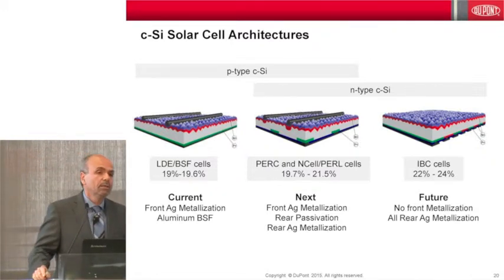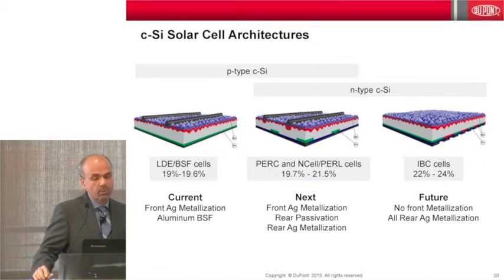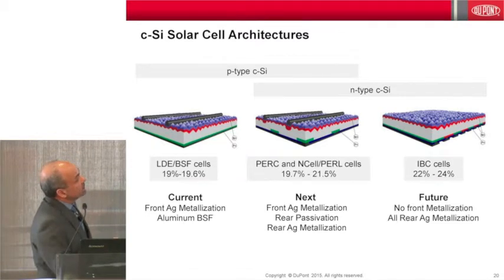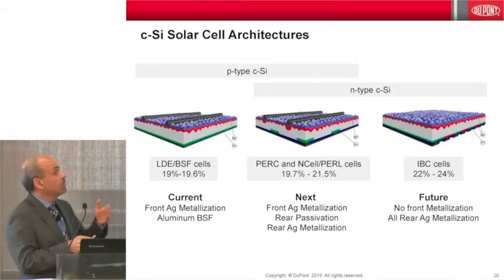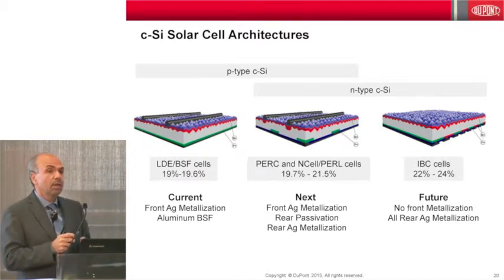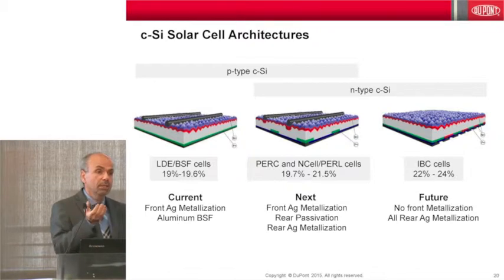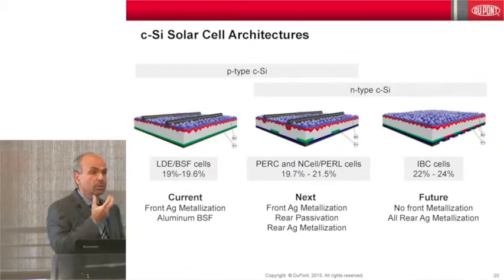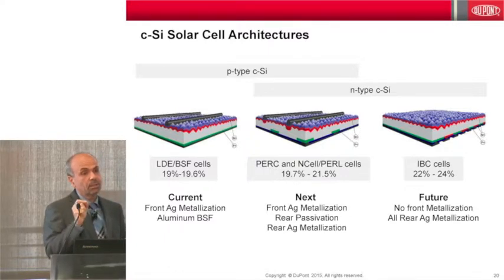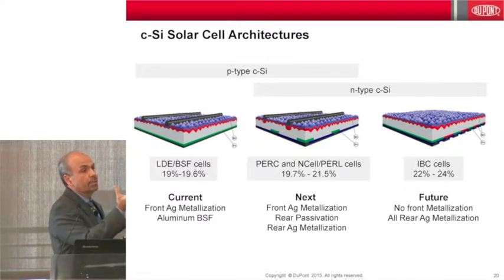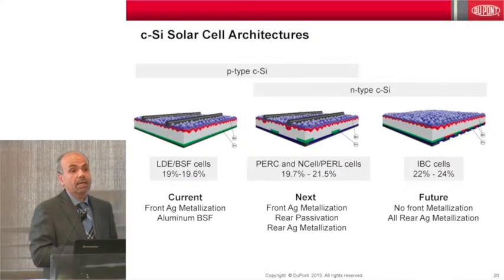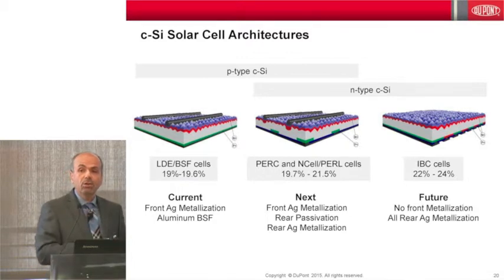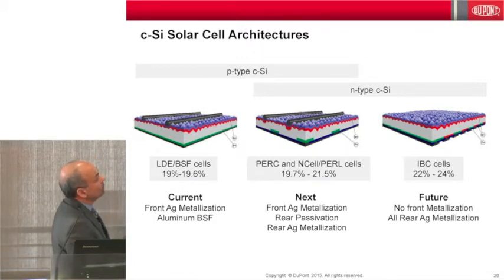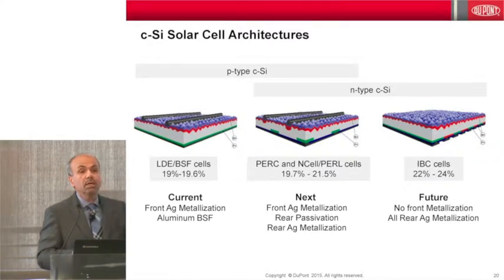contributes in a negative way towards the recombination, to use a technical term, for the positive and negative carriers in the cell. So what the industry is doing today is to passivate the rear side the same way we have been passivating the front side with silicon nitride. Now we also passivate the rear side with silicon nitride and aluminum oxide, and then we drill holes for allowing the aluminum, specially designed aluminum, to selectively contact the rear. Only 5% of the area is contacted. So that gives you superior performance in the rear, and you have efficiency improvement. So you can see that you can go from 19.5 all the way up to 21 plus with this device